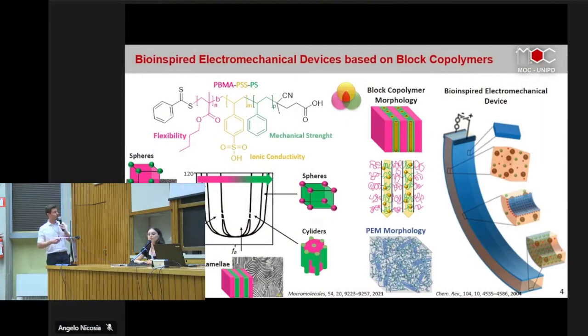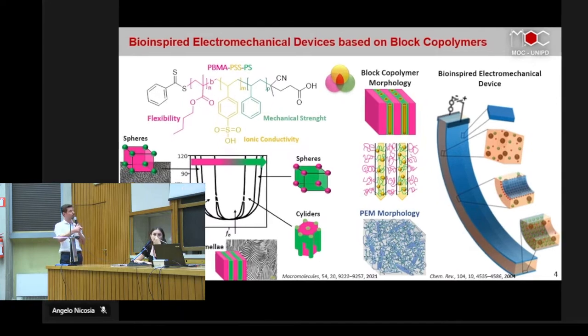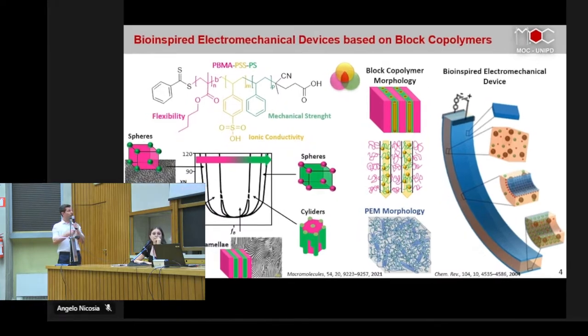So the most important here is that by controlling the molecular weight, you can control the morphology. So you can have spheres, cylinders, lamellar, basically by the size of the blocks. Because, for example, if you imagine they have the same molecular weight, the interface between them will be flat. In this case, we have a lamellar. So as soon as you start to increase one of the molecular weights, it starts to overlap, making cylinders, and finally spheres.